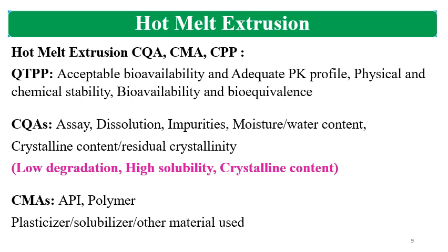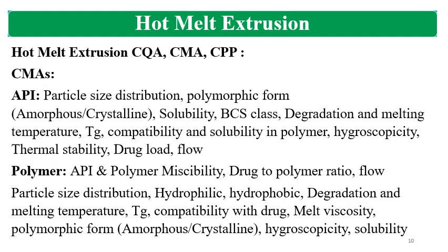CMAs apply to the API, polymer, and other additives. CMAs of the API include particle size distribution, polymorphic form (whether amorphous or crystalline), solubility, BCS class, degradation and melting temperature (which guides the processing temperature), glass transition temperature (Tg), compatibility and solubility in the polymer, hygroscopicity, thermal stability, drug load, and flow. Drug load refers to the dose relative to the total weight of the formulation unit, whether tablet or capsule.